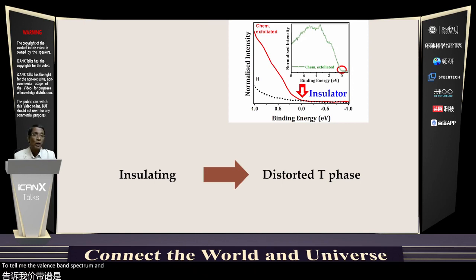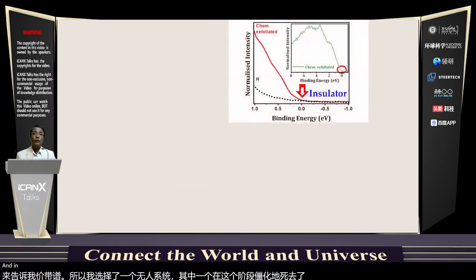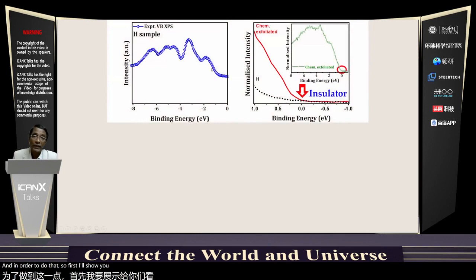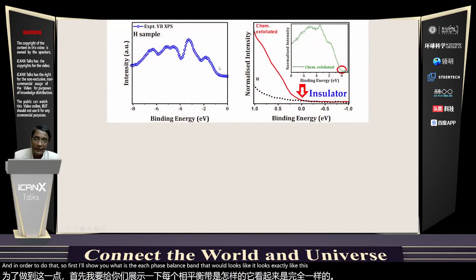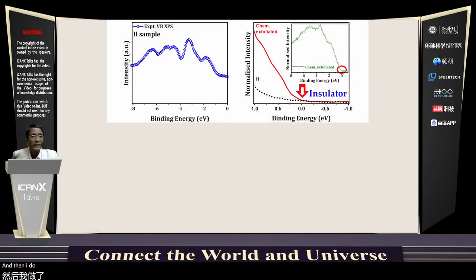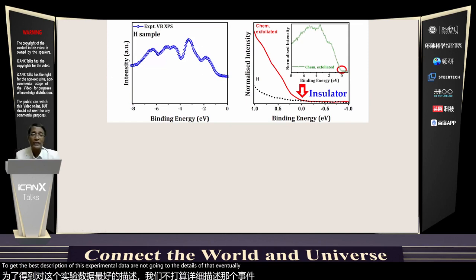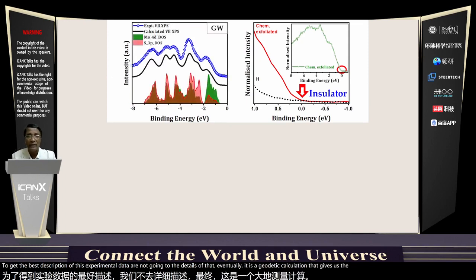And so I take a known system, molybdenum disulfide, in the H phase. First I show you what the H phase valence band looks like. It looks exactly like this. This is the experimental data. And then I do various levels of approximation, making it more and more complex, a more demanding calculation, to get the best description of this experimental data. I'll not go into the detail of that. Eventually, it is the GW calculation that gives us the best data, and I'm showing you the result.